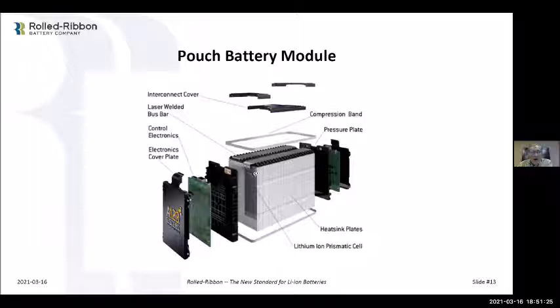It also armors up the cell, which is a soft pouch, and it's therefore vulnerable to shock and vibration and other things. So they put an aluminum sleeve around that. Well, that adds to weight and mass and size when you put it in there, and it's actually fairly ineffective because there's an air gap.